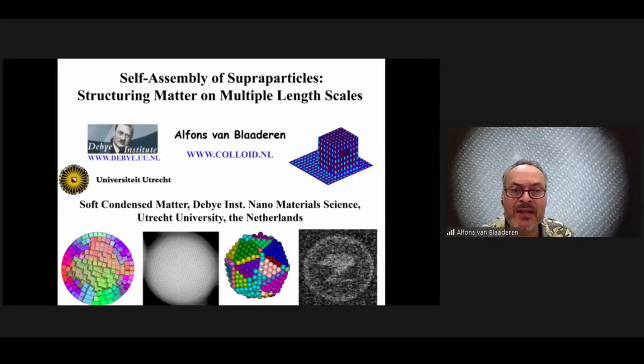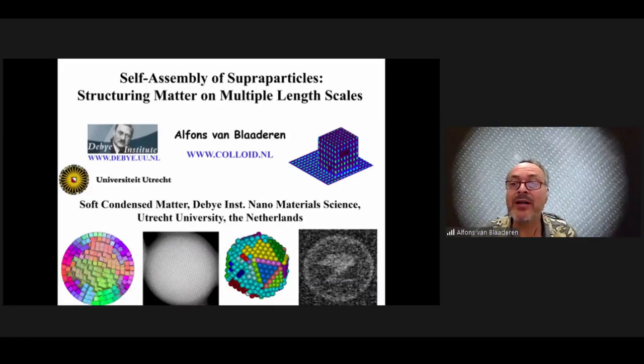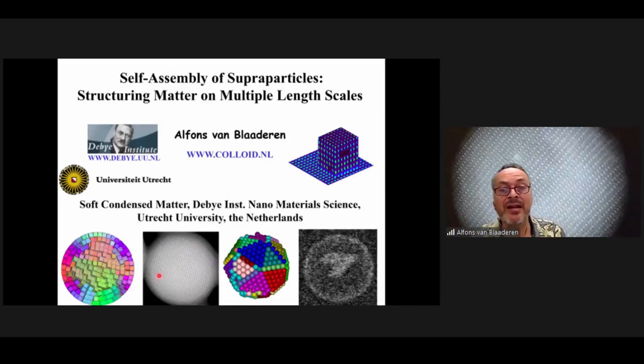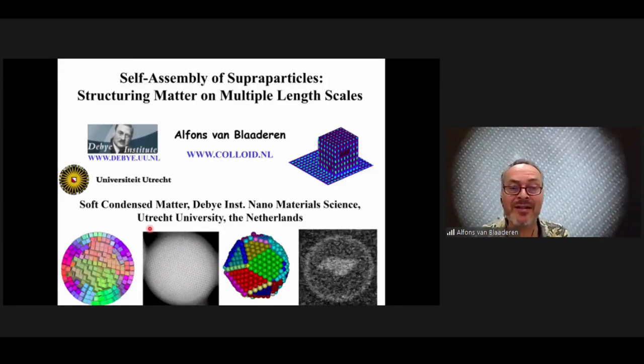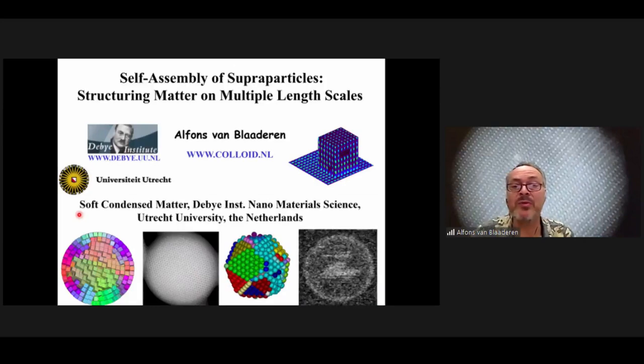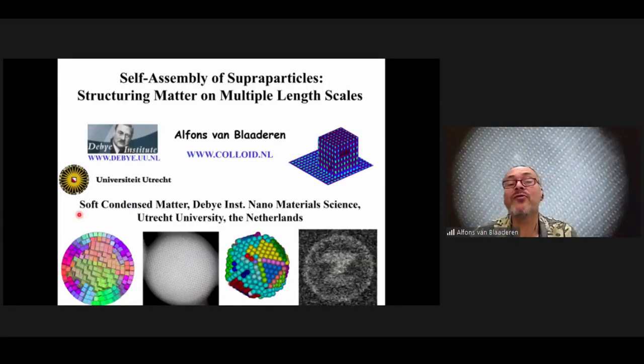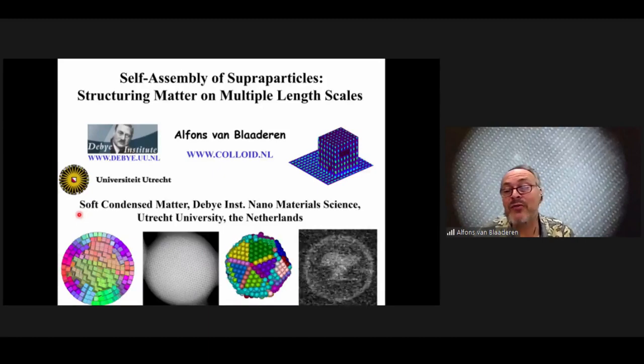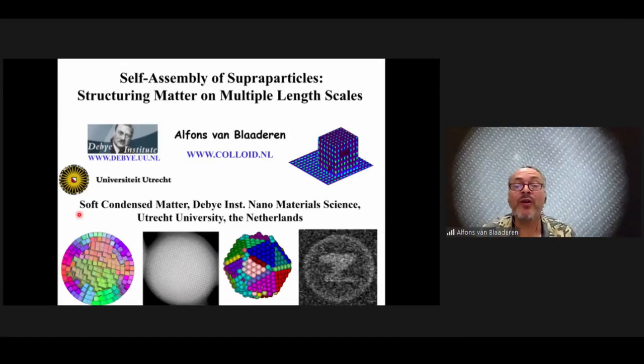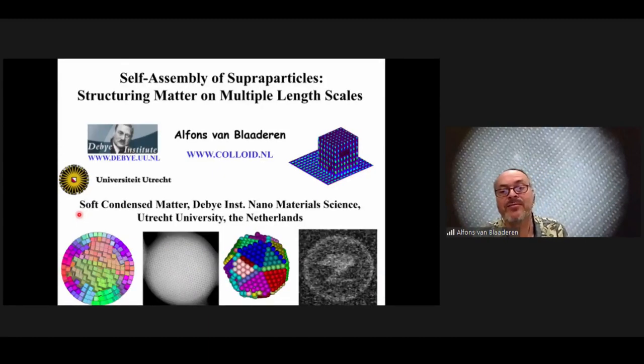It's important to mention as well that all the supraparticles I'll be talking about, and even the one that's right back to me on the screen, is itself still a colloidal particle. So built up from nanoparticles, and the supraparticles that I'm showing you here, if I highlight it with the laser pointer, these particles here are a few hundred nanometers in size themselves, so we can do a further self-assembly step. So what I hope to convince you of is that these supraparticles and their self-assembly is a very powerful way of structuring matter at many length scales.